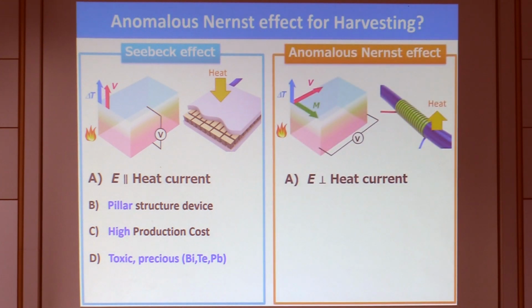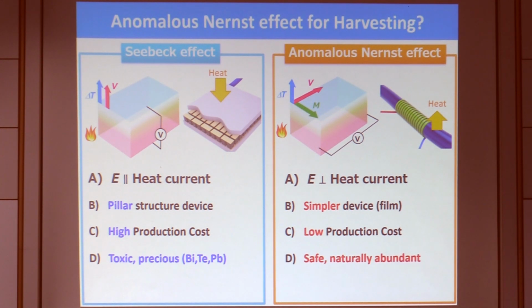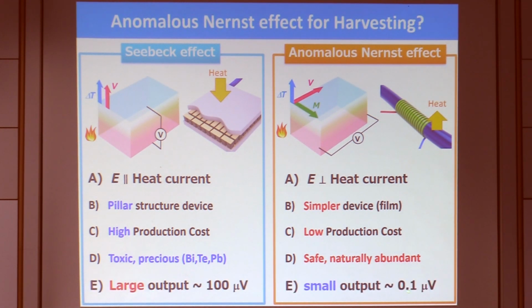Now we look at what we have been talking about in this session, the anomalous Nernst effect. This turned out to be quite interesting, really, and maybe useful if the power becomes much larger. Namely, the electric field or voltage is perpendicular to the heat current direction because of magnetization, and that is quite useful for making a very simple thermoelectric generator. That actually suppresses a lot of the production cost, and obviously a number of possible materials can be used. Namely, one can use naturally abundant, safe materials, but nobody has ever paid attention to the anomalous Nernst effect because the output is too small, right?